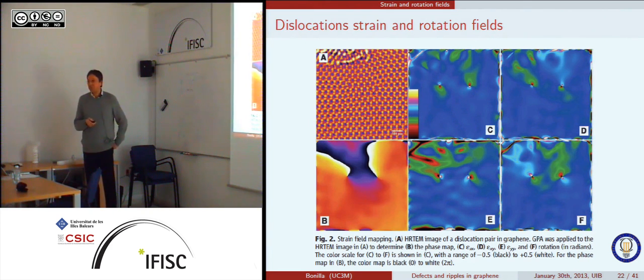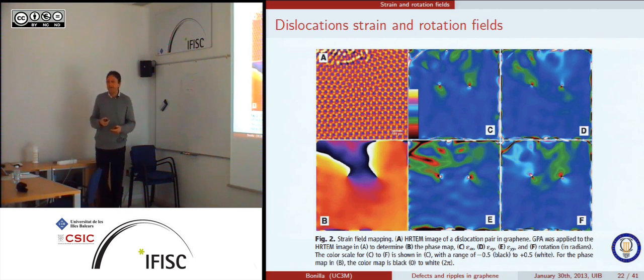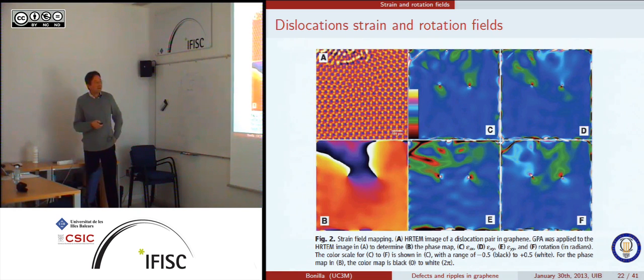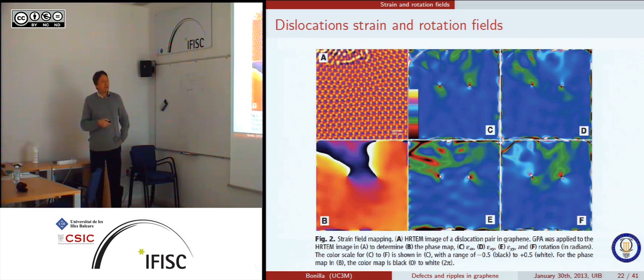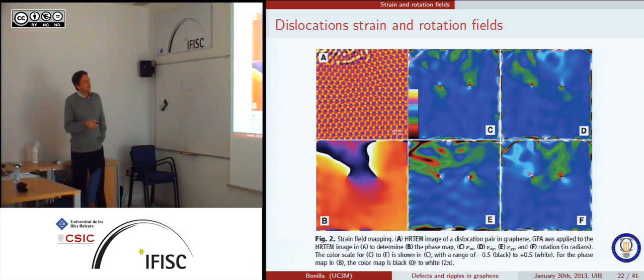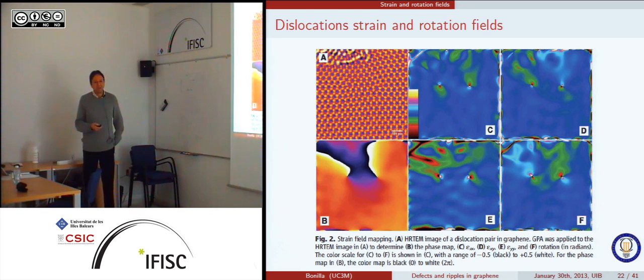Now you take one of them and put a Gaussian mask on top of it. Turns out that the phase of that gives you the displacement vector projected on the corresponding primitive direction. Now you do that with vectors corresponding to the basis of the primitive of the lattice. You can reconstruct, out of the information of the phase of the Fourier transform, the displacement vector. Then you take derivatives and you get the strain along the x-x direction, along the xy, and along the yy, and you also see these rotation maps. So this rotation is just the antisymmetric part of the gradient of the displacement vector.